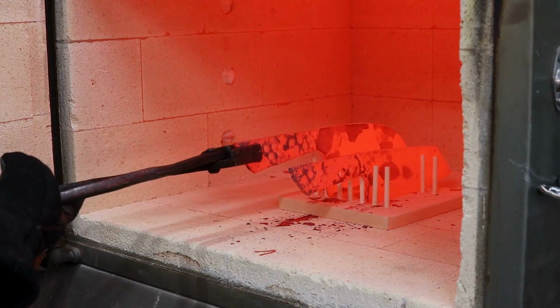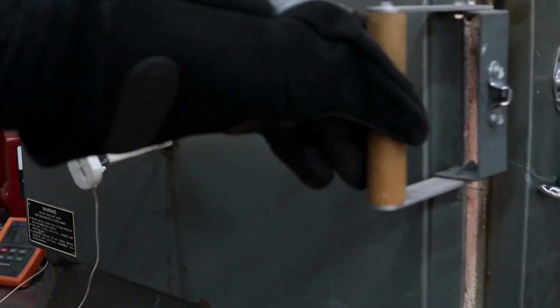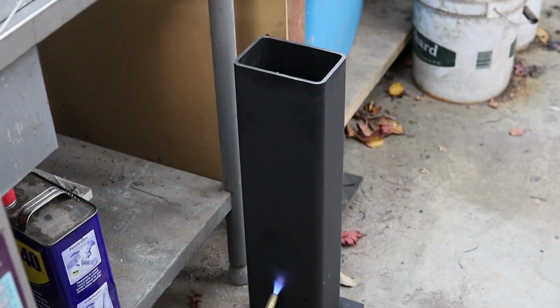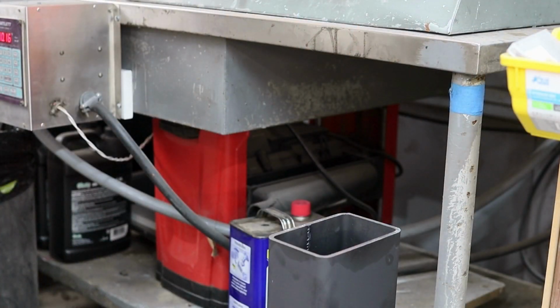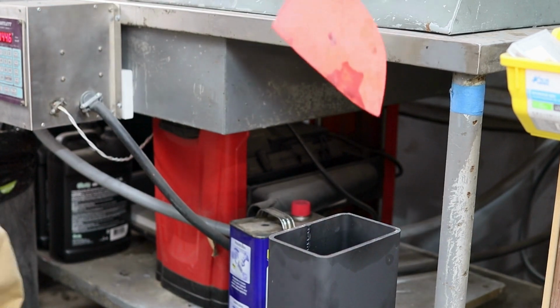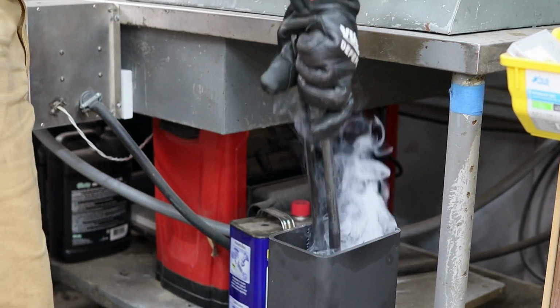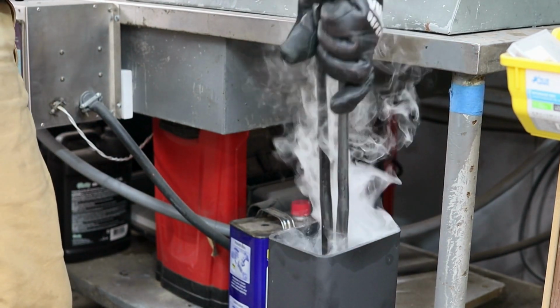There's a little peek at a custom bunka knife that I was normalizing as well. I'm heating my quench tank of Parks AAA with a torch. I shoot for around 120 degrees Fahrenheit when I quench a blade. I'm quenching this blade at 1525 degrees Fahrenheit.